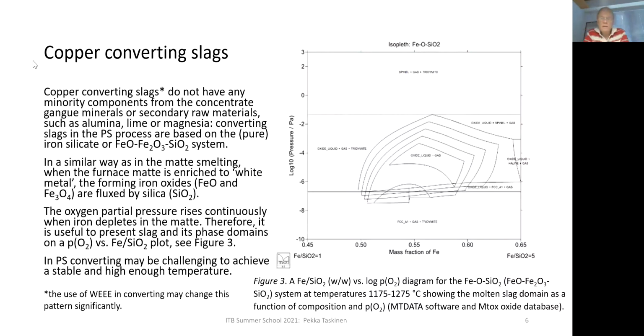What kind of slags are we using in the converting step? Now we don't have any more these gangue minerals which are in the concentrates. So we are having only those materials in the converter charge, which dissolve in the furnace matte. So we have typically, along with copper and iron and sulfur, we may have nickel, we have precious metals, we have platinum group metals, we may have cobalt,